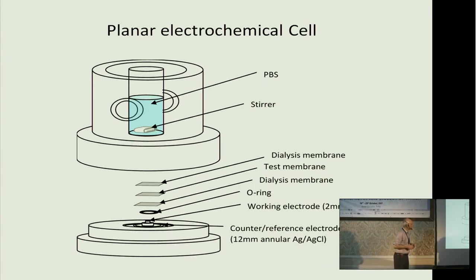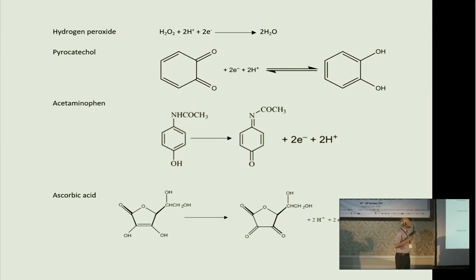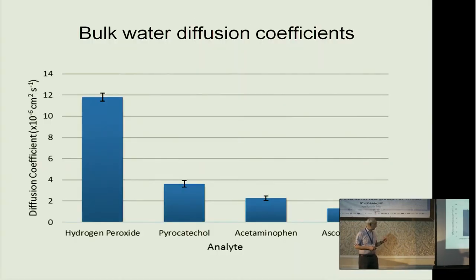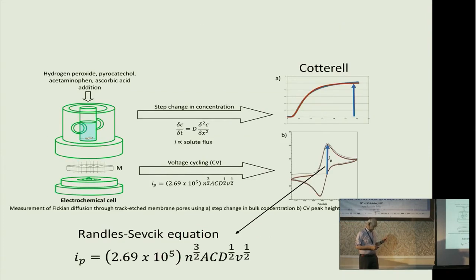Our experimental setup is there. There's the membrane there, and it's protected by dialysis membranes, and we do electrochemistry on it, just like that dynamic modeled response that I showed you. And we picked the easiest and simplest small molecules. These should not be affected by anything on that pore diameter size. Pyrocatechol, paracetamol, ascorbic acid, and peroxide. It couldn't get easier in terms of electrochemistry. This is baby electrochemistry. It cannot go wrong. Or can it? Yes. Well, okay. My experiments are better at, let me tell you.